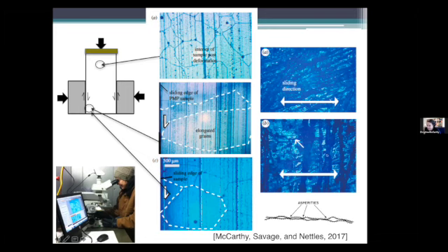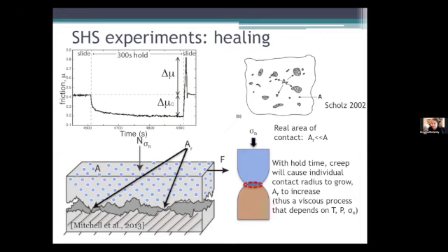And at the end, just in case you're wondering what's happening during sliding, we see a lot of the same macro or larger wavelength grooves that we've created. They persist. But I could say that some of these low amplitude areas in between, like if you're looking at this cartoon, you know, that these remain, but some of these low amplitude curvature seem to grow, and you have grain growth at the interface through the course of an experiment. And likely that is due to this healing that I talked about.